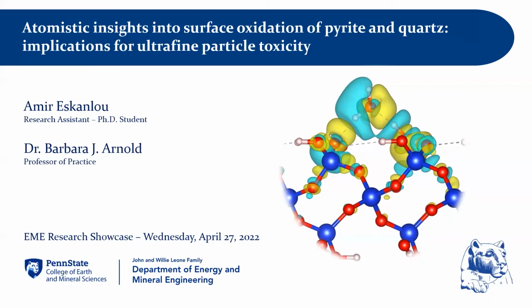For our simulation, we used the 100 pyrite surface and also the 001 surface of quartz, and they interacted with water molecules and oxygen molecules. We ran the simulations for about 5 picoseconds, which is 5,000 femtoseconds or 5,000 electronic steps. After obtaining the ultimate geometry, we did the ground state DFT calculation to find the ground state energy of these geometries. And then we compared the interaction energies, both for silica and pyrite, when they interact with water molecules and also when they interact with oxygen molecules.